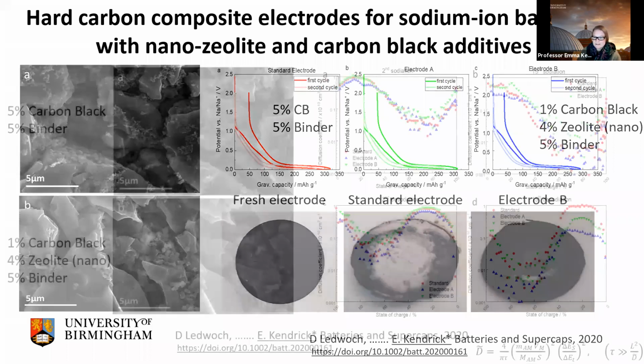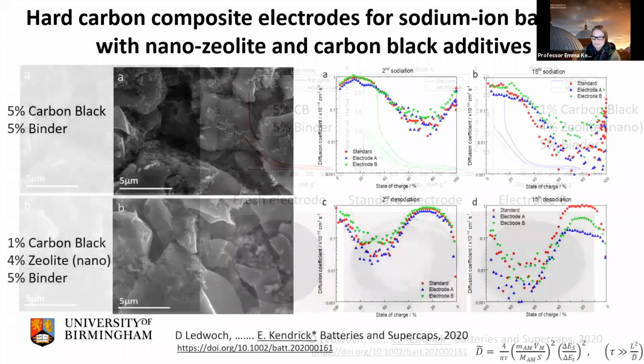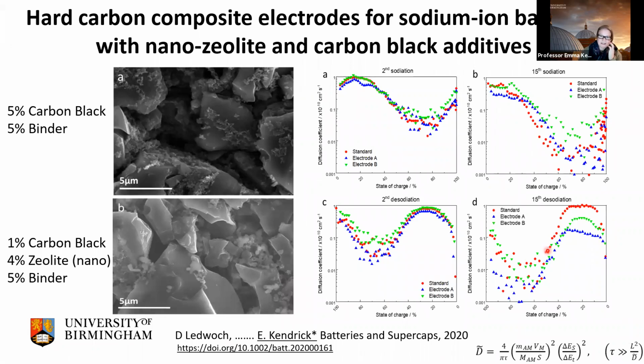And we did quite a lot of work looking at the specifics of the diffusion. And this is some diffusion coefficient calculations that we got from galvanostatic intermittent titration technique, GITT. And you can see again here that this higher diffusion coefficient rate is the sloping voltage profile, and this very low diffusion, 2 orders of magnitude lower, happens on the plateau region, on that low plateau region.